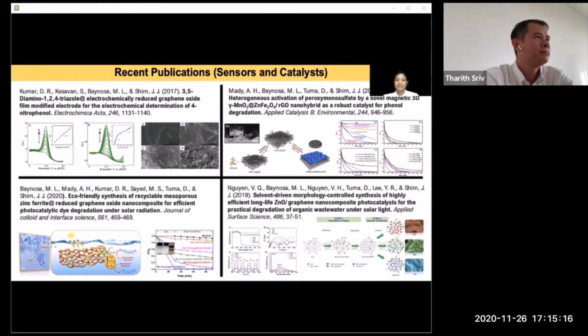In the last study, we focused on the effects of varying the solvents in the synthesis of zinc oxide and graphene nanocomposites. The use of pure water, pure ethanol, and their combination resulted in three different kinds of zinc oxide morphologies, which in turn yielded different results in terms of degrading dyes under solar irradiation.